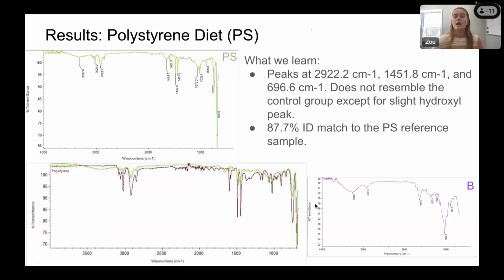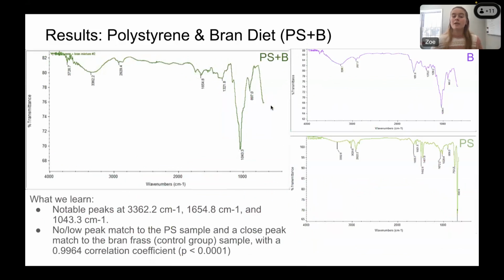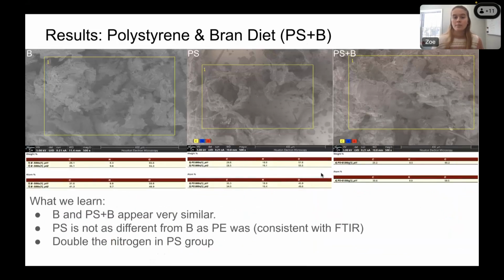As for polystyrene, we can see that there are peaks that do not match the control group, but there is an 87.7 ID match to the polystyrene reference sample. But the polystyrene and bran mixture has the same peaks as the bran sample, with the same peaks in the hydroxyl region and the fingerprint region. And that has a correlation coefficient of 0.9964 to the control group and a very, very low peak match to the polystyrene group. As for the SEM, again, the bran and the mixture look very similar, and the nitrogen level of the polystyrene group is almost double that of the control group. So again, we're looking at that nitrogen metabolism explanation.